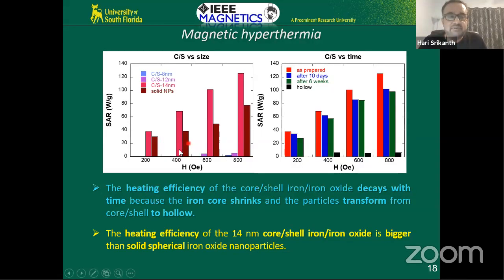For example, we wanted to get a higher SAR compared to the solid oxide particles. You can see that the core shell particles definitely are much better. As you would imagine, the iron has a larger magnetization, so it's much better. However, look at this graph here as a function of time. In this case, this is for one batch, and the time scale varies, so it's not very predictable. You can see that as a function of time, the SAR goes down, and eventually when it becomes hollow, it doesn't heat up at all. So it's not useful for nanoparticles.